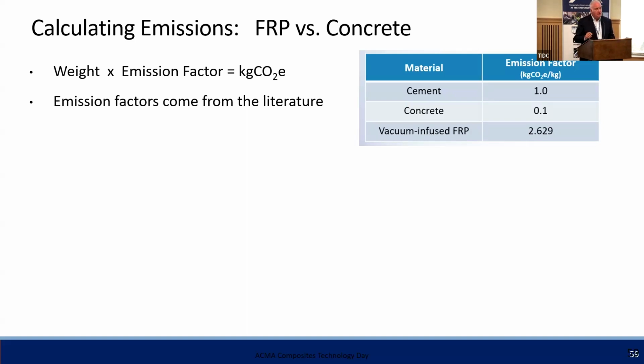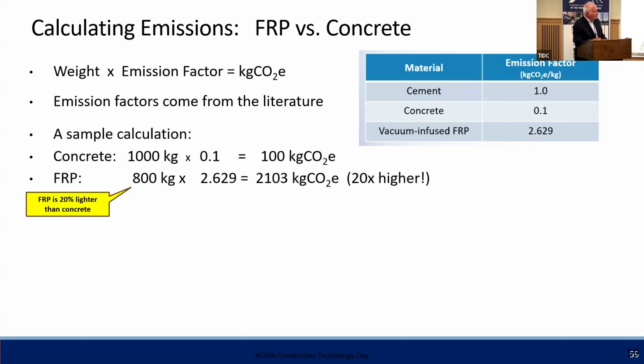And remember, you don't build structures with cement. You build structures with concrete. And concrete is only about 10% cement. So the emission factor for cement is 1, but the emission factor for concrete is 0.1. And that order of magnitude makes a huge difference when you're doing calculations. Let's do one. Again, I'm going to take a 1,000 kilogram part with concrete, but I only multiply it by 0.1 and I get 100 kilograms of CO2 equivalents.